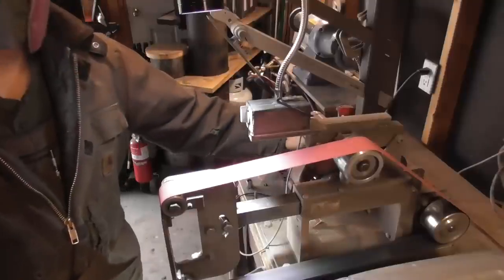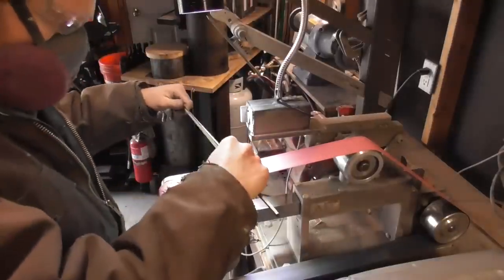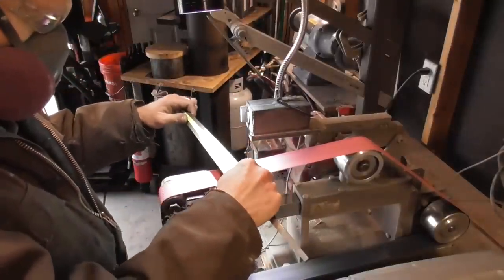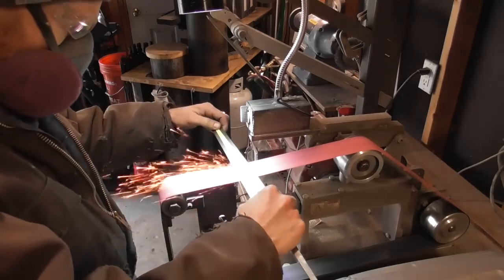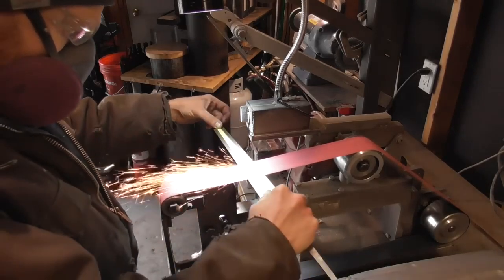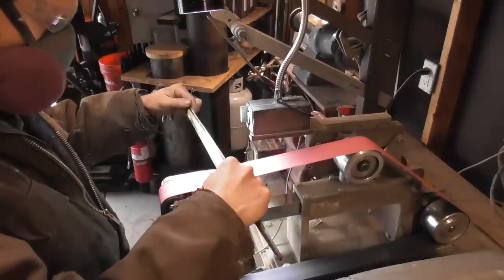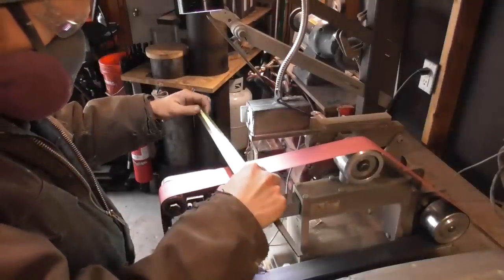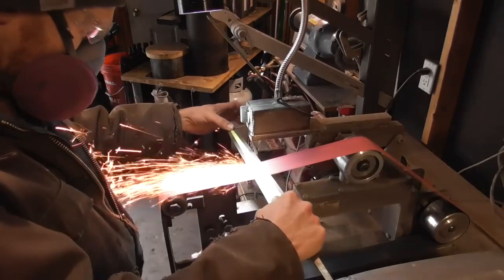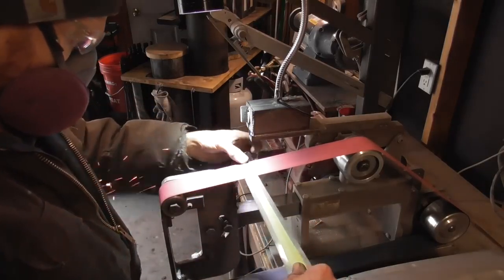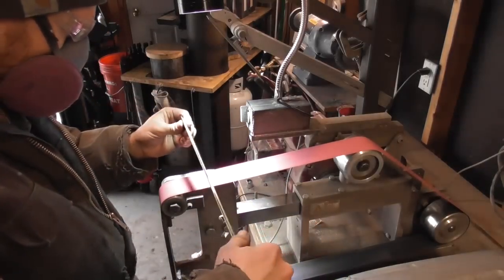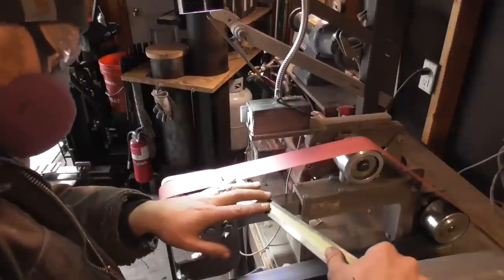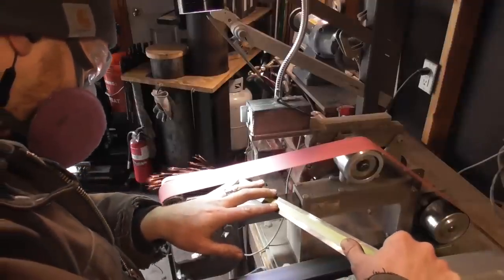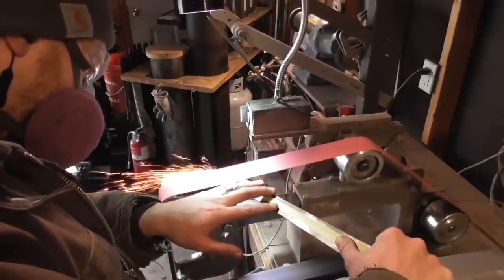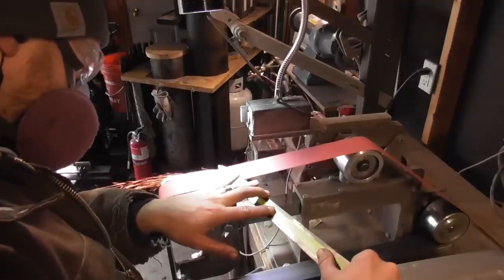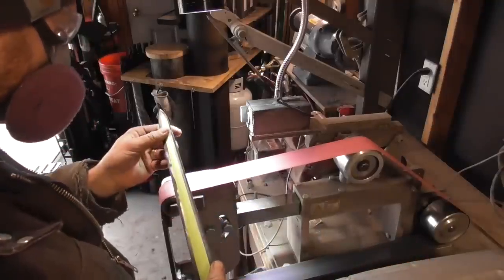After all of that is done, it's time to start actually putting the edge on the blade. So you can see that I taped the ridge line of the dagger to keep it from being ground away by accident. And I'm putting a convex edge onto the dagger. This increases strength. It's going to put a little bit more mass behind the edge. And I found that that almond shape on the edge is really the best shape for a lot of different things. It provides a stronger blade, and you're still able to get a really thin, sharp edge, so it's still good at slicing.